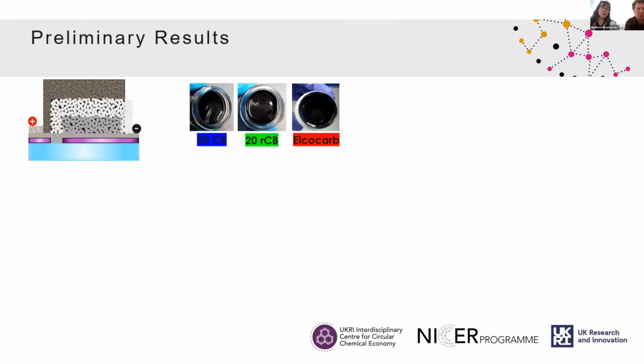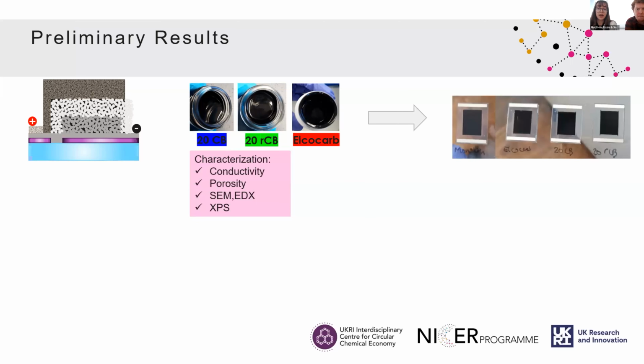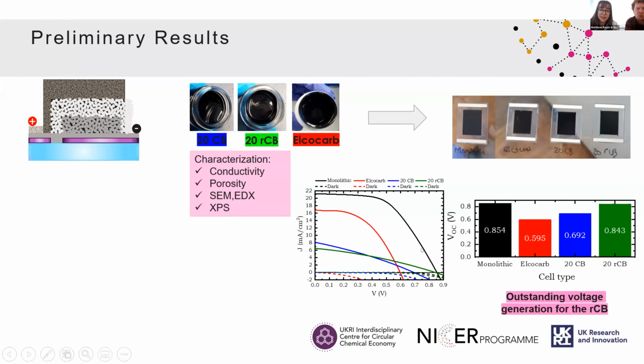So basically what we did, we made different pastes using virgin carbon black, which is the 20 CB, recycled carbon black, which is the 20 RCB, and the ElcoCarb, which is a benchmark, a state-of-the-art commercial paste. We built them into solar cells. So we had a reference, number one, the monolithic, which would be the full stack that is optimized, and it's purchased from the same company that produces the ElcoCarb. And then the other three, which are also purchased, are up until the zirconium layer, and then we deposited our carbon paste. And what happened was very interesting.